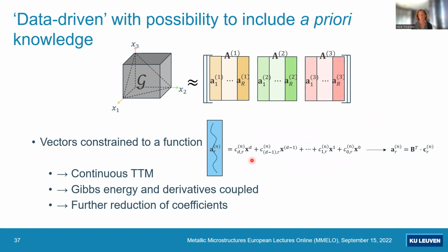with this function. And if we just evaluate the function, we have Gibbs energies. But if we first take the derivative of that function and then evaluate it, we have the chemical potentials, and they are fully consistent with the Gibbs energies that we are using. And we also optimized all these data points using computed Gibbs energies and computed chemical potentials. And so I think if you exploit this further, it will give you a very nice and very consistent description of physical data. So that's also why we want to continue with this method and also, for example, develop it for sublattice models and so on.